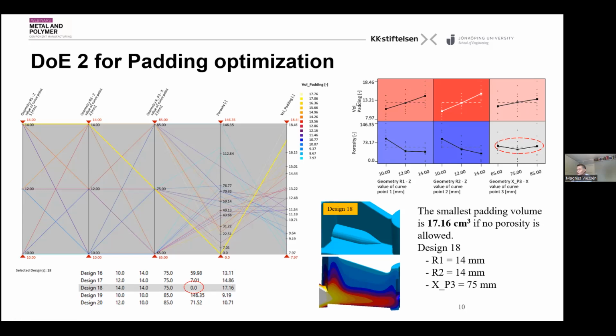And the good thing is that now we have found something where the trend is that this value seems to be where we really minimize the porosity. So it's most likely this optimum location, more or less. It may be 68 or something, but roughly this location. And we have found a design which has given me 17 cubic centimeters instead of 14, which was the initial design. Now, by only increasing the padding material by a few percent, we can really define the design which is robust with respect to all the variation in the foundry.